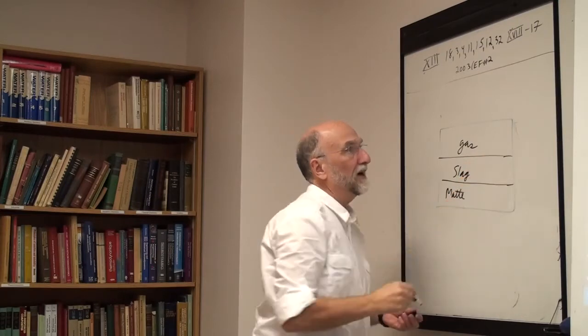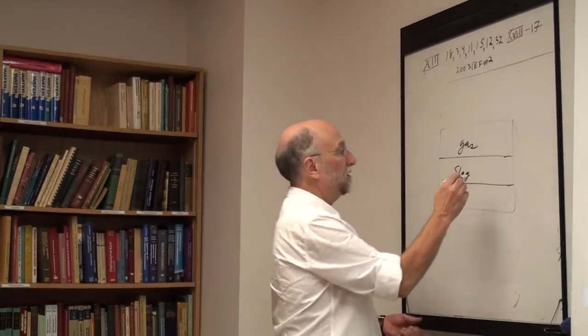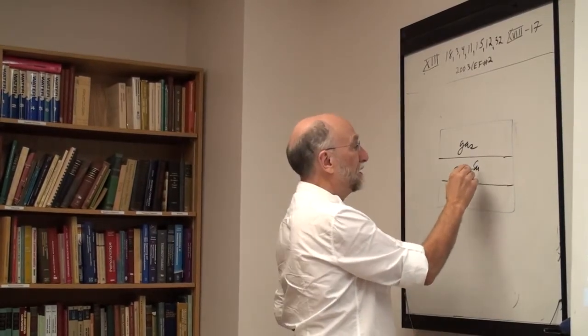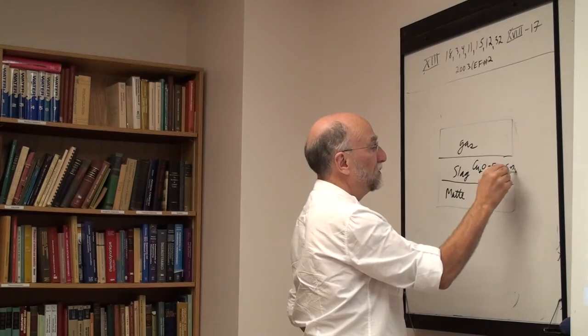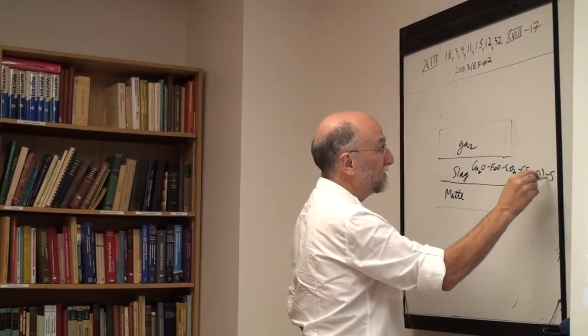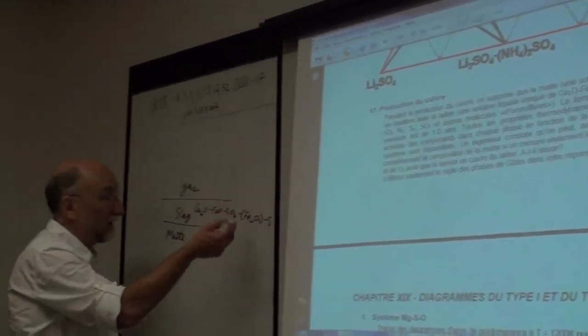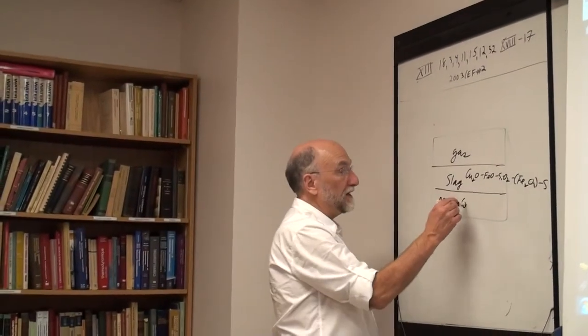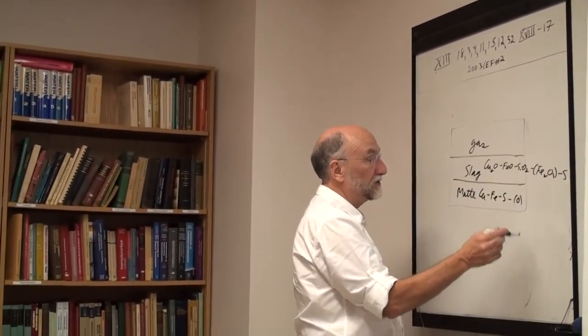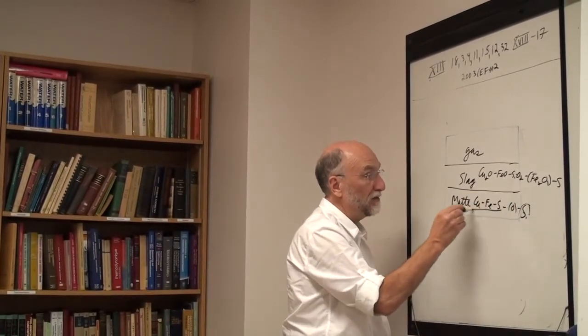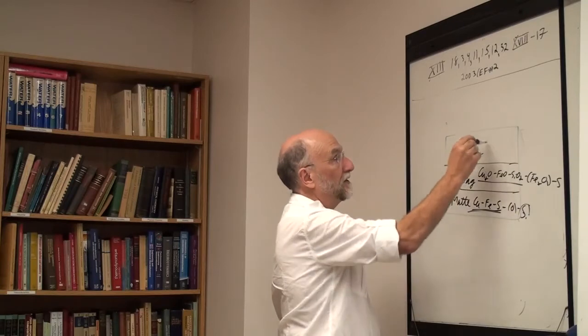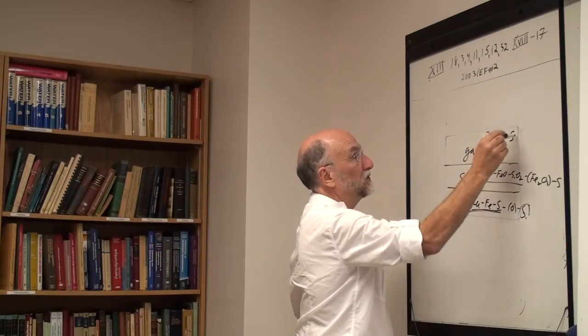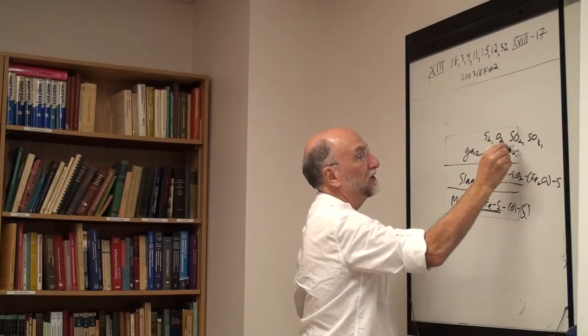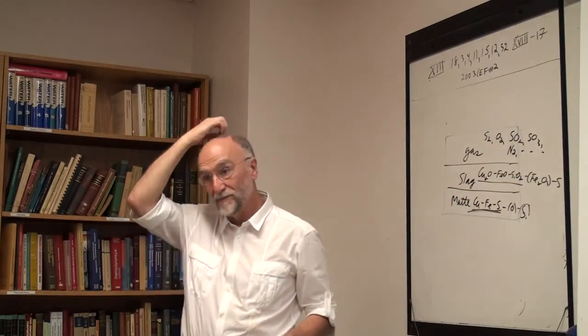The slag phase would consist of copper oxide, FeO, SiO2. It also has some Fe2O3 in it, of course. It's got sulfur in it. It's got all the things dissolved in it, but it's principally copper, iron, silica, and it's going to have trivalent iron and sulfur. The matte is mainly a copper, iron, sulfur solution, but it's also going to have oxygen in it, and a little silicon. Everything's going to be dissolved, but it's mainly copper, iron, sulfur. And the gas phase contains everything: S2, O2, SO2, SO3, nitrogen, and a whole bunch of other stuff. And the whole thing's in equilibrium.